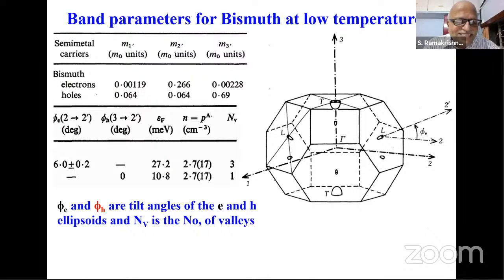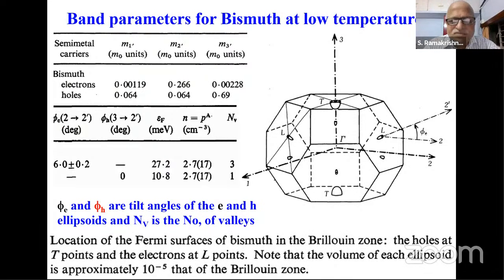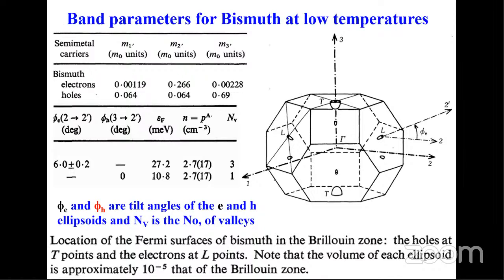Since bismuth has been studied for 100 years, everything is known. Its Fermi surface is known, and it so happened that it has a very tiny Fermi surface. You see these small blobs, which I'm pointing out. These are hole pockets, extremely small, and these are electron pockets. There are 3 electron pockets and 1 hole pocket, which occupy only about 10 ppm of this Brillouin zone. So it's a tiny Fermi surface. And I'm going to show you that such a tiny Fermi surface, with both electrons and holes together, is what is responsible for superconductivity.